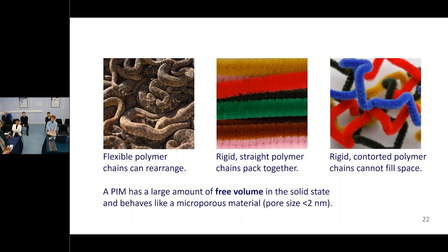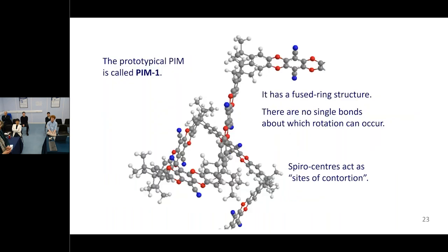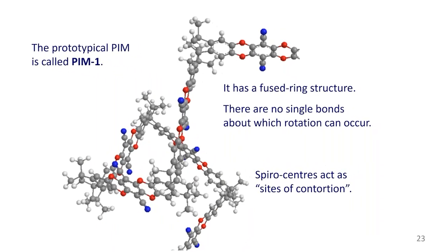So the prototypical example of a PIM is the one that we call PIM-1. It was the first one we made. We made a series of related polymers. And in the structure here, you can see that the backbone is all rings. It's either carbon rings or rings with a couple of oxygens in them. But it's all rings. There aren't any single bonds that rotation occurs around. But we have these units that give almost a 90-degree bend at intervals. And that comes from spirocenters. A spirocenter is where we have a tetrahedral carbon atom attached as part of two ring systems, in this case, five-membered ring systems. And so that sort of structure gives us this wiggly, contorted structure, but without the conformational flexibility of a normal polymer.